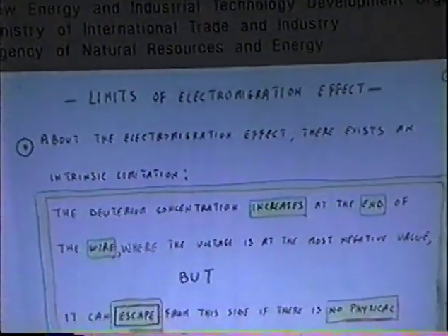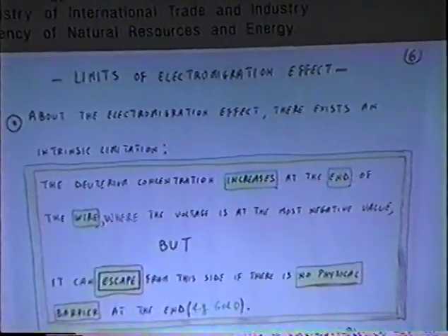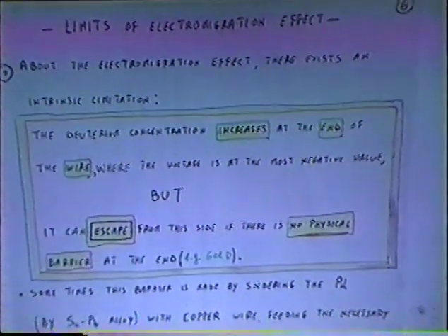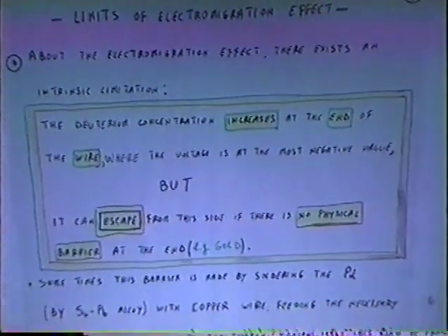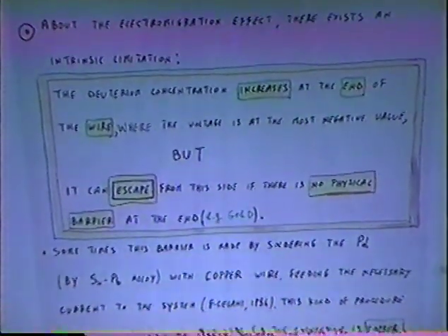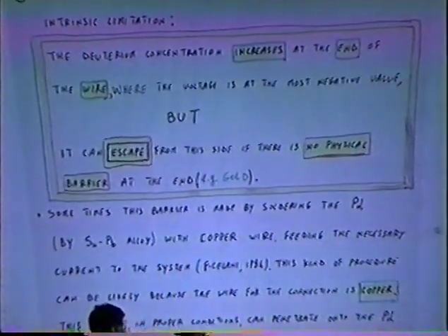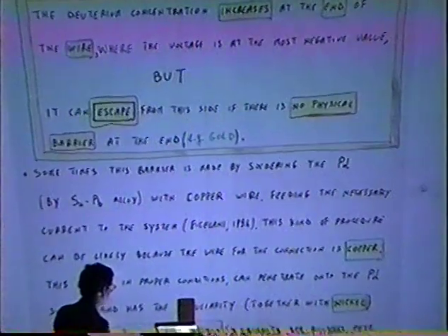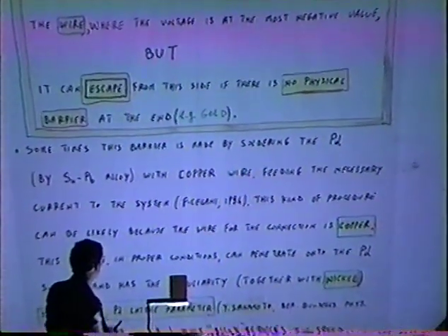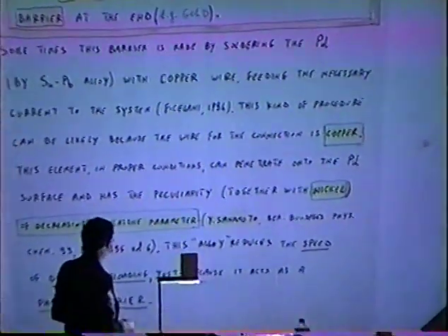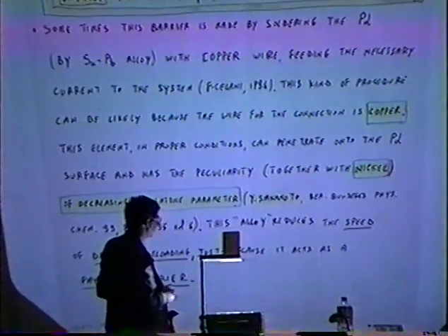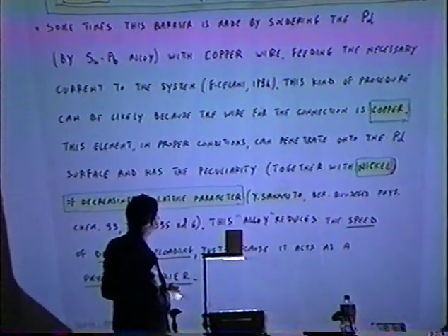The electromigration is a very powerful tool, but has one very big drawback. You increase the concentration to one side, but after you have escape of the deuterium to the bottom of the wire. So it's necessary to make some physical barrier to avoid the loss of loading. Usually people use gold, we use copper or nickel, because copper nickel has the advantage of reducing the lattice parameter of palladium.